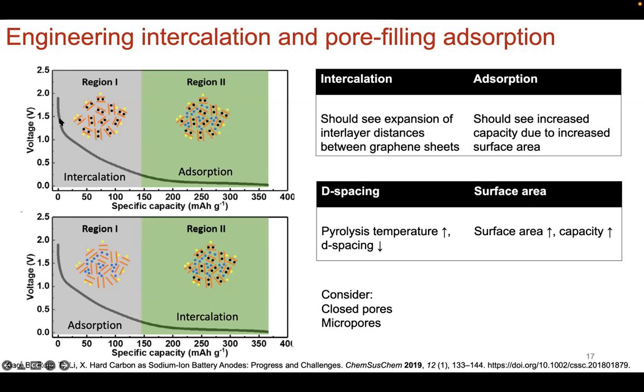And so you see some stark differences between the voltage profiles, which tells you that there's going to be differences in the crystal structure as we know, the thermodynamics as we know, the kinetics as we know. So everything's all intertwined. And one school of thought, which was the original school of thought back when Jeff Dahn was studying these, and even before Jeff Dahn actually, several folks have studied over the years, but it could be subscribed that the sloping region is more that of intercalation. And we've seen that, right? We've seen the sloping voltage curves as indicative of a solid solution intercalation mechanism.